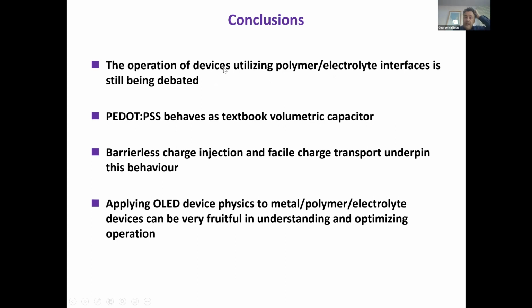So to conclude, the operation of devices using polymer electrolyte interfaces is still being debated, the mechanism of operation. PEDOT is a shining example that behaves as a textbook volumetric capacitor. You can understand this behavior because charges, whether electronic or ionic, can enter the film without facing any barrier, and there is facile transport of both these carriers in the film. And what I advocate is that applying the device physics that we learned from OLEDs to metal polymer electrolyte devices can be fruitful for understanding and optimizing their operation.